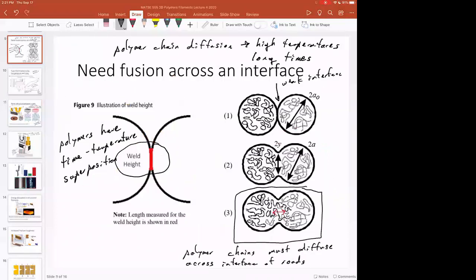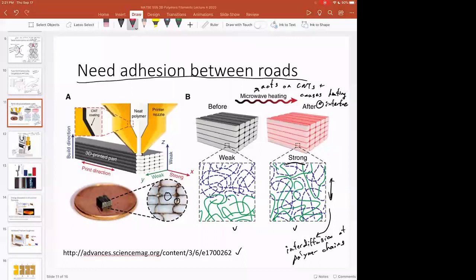So if you need to make all these interfaces strong, and if you heat only right here where the CNTs are, you can get this interdiffusion to happen. And that's exactly what they did in this nice paper here. Now, they had to do a lot of things to make that happen, namely coating their filaments in carbon nanotubes, but this is a demonstration of localized heating causes this strengthening of the part at all these interfaces.